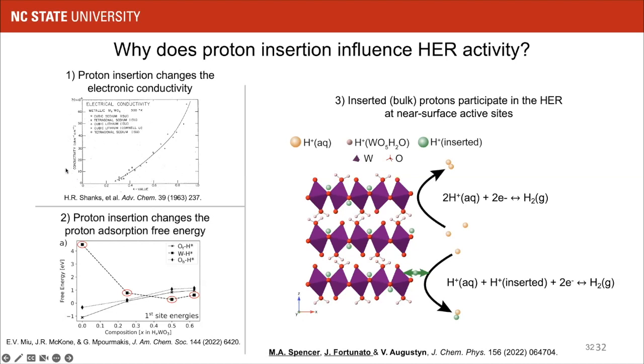One idea that's been around for a very long time is that the proton insertion changes the electronic conductivity, like the work that I showed you at the very beginning from the Yildiz group. Tungsten oxide will go through a semiconductor to metal transition. In thin film materials, though, we would assume that the electronic conductivity is relatively good.